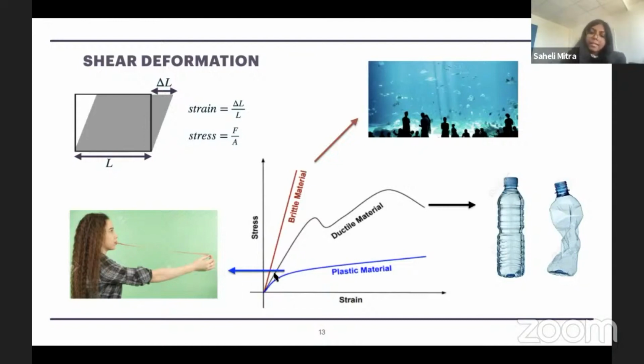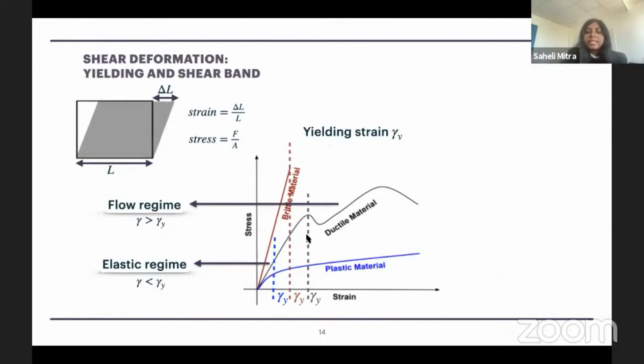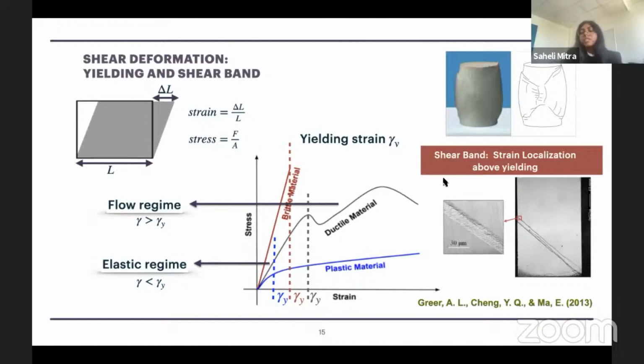Yielding is defined as the transition between the elastic and the flow regime. In the elastic regime, if I remove the load, the system can go back to its initial state, whereas in the flow regime, it cannot. Another interesting occurrence in the high strain flow regime is the appearance of shear bands. What happens if my strain is too large? In the system, we get to see permanent deformation where strain is localized.